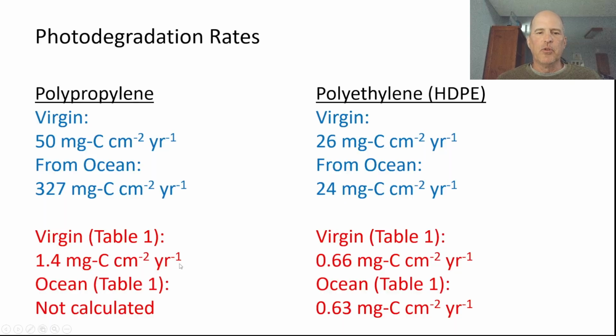So what they report is 1.4 for virgin. They did not calculate for ocean polypropylene because of the nonlinearity, which is fair. 0.66 for virgin polyethylene and 0.63 for ocean polyethylene. In all cases, it's about a factor of 40 different. I can't figure out why. I can't come up with even some reasonable suggestion for why.